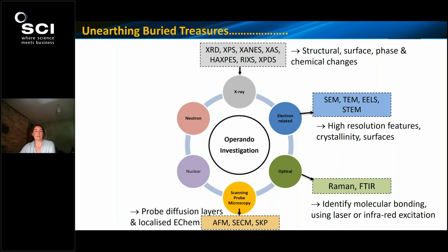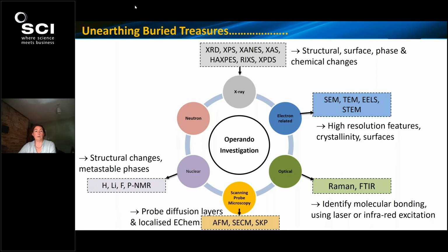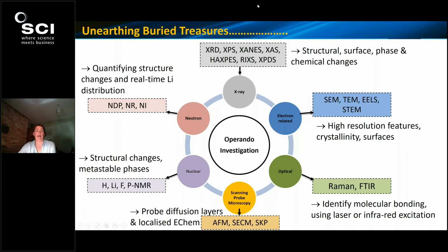The scanning techniques can look at things like probing diffusion layers or localized electrochemistry mapping. Techniques typically such as AFM, or atomic force microscopy, scanning electrochemical microscopy, and SKP. We can also look at structural changes and metastable phases with things like multinuclear NMR techniques, which have been very useful at looking at metastable phases. Cambridge have made very, very good progress in this area. And then finally, the neutron-based techniques can quantify structural changes and look at real-time lithium distribution. So all of these have made enormous leaps and bounds in our understanding of degradation modes since their development.